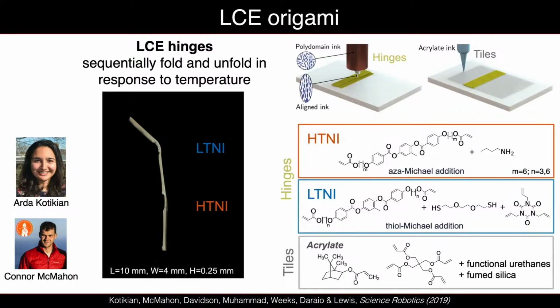And this is just a simple tri-layer structure, whereas if it folded together with these two hinges, it would form a triangle if they were made out of the same TNI. But because there's a sequential folding to this, because as we're heating, the low TNI goes first, we can fold this into more of a paperclip kind of architecture. So you can see that first folding, and then the second triggers.